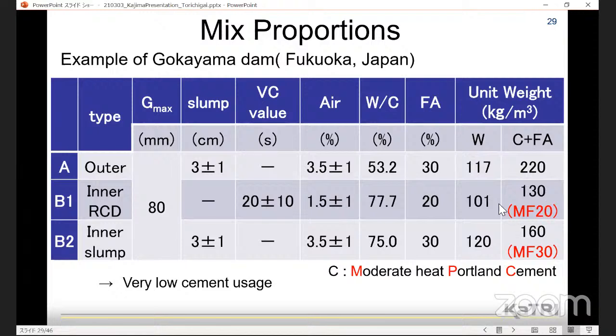Then the unit water volume of RCD concrete in the inner part is 101 kilograms per cubic meter. The amount of water in RCD is very, very small, like this. The unit cement amount is 130 kilograms per cubic meter, and the cement is called MF20. M shows moderate heat portland cement, and F shows fly ash, which is made by substituting 20% of fly ash for moderate heat portland cement. And MF30 is 30% fly ash.